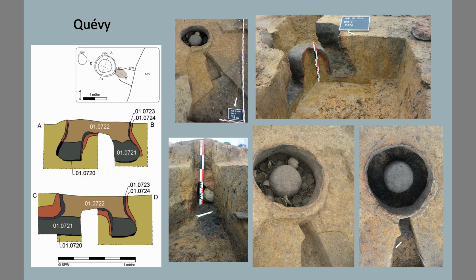The second kiln, the one of Quévy, was excavated in 2015. It was found in a silty soil. It consists of a circular chamber with an internal diameter of 80 centimeters, preserved to a depth of 60 centimeters. To the east, the stoking channel is short and very narrow. It leads to a work area that was quite well preserved. The lower part of the combustion chamber is excavated in a bell-shaped profile, and the central pillar is preserved in the silt. The bottom of the chamber is practically not rubefied, unlike the side walls and the central support, which are rubefied to a thickness of 2 to 5 centimeters.